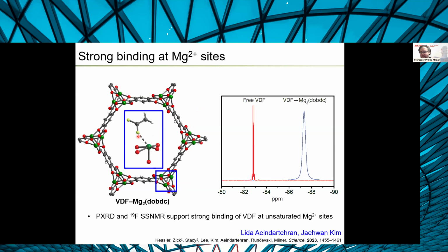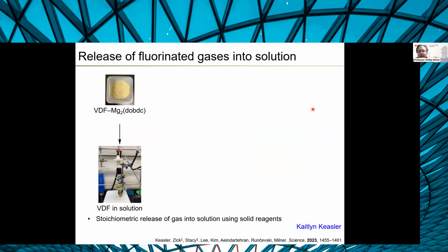We can also support that by solid state NMR as well, where we see, when we look at the free gas here, and we dose it into the MOF, it shifts upfield from the shielding effect of the linkers, and it broadens because it's now immobilized in the MOF. So both of these techniques show us this MOF has a very strong interaction with this fluorinated gas. Now the question is, can we get it back out?